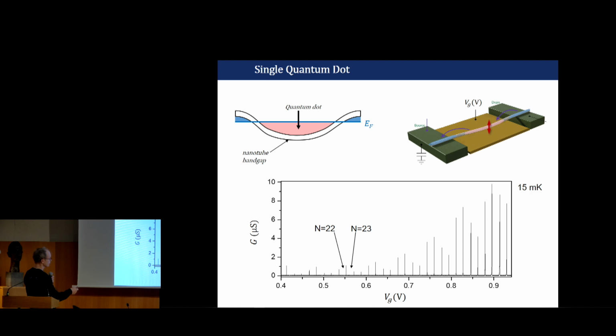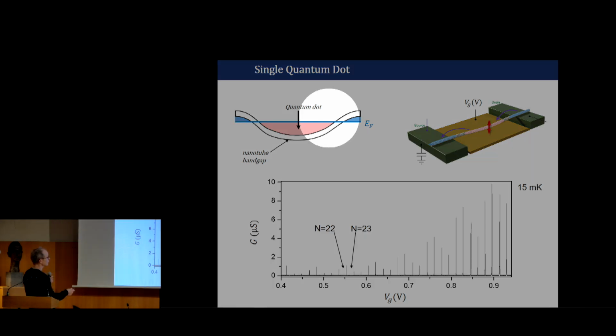And here, we measure the electrical conductance, which is the inverse of the resistance, through the nanotube as a function of the voltage applied on the gate, at the bottom of the trench.